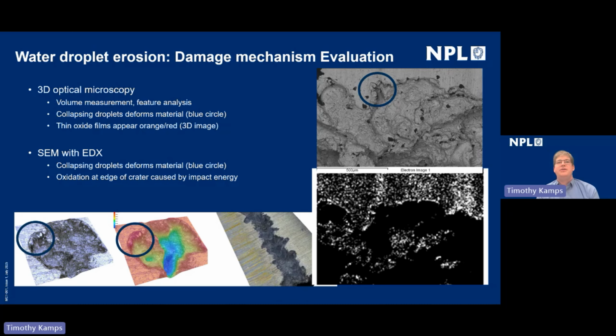And you can see the blue circle identifying a region on the 3D images at the bottom left of the slide, with the scanning electron microscopy image on the right-hand side of the slide. This scanning electron microscope also had the ability to use EDX, energy dispersive X-ray spectroscopy, to identify elements on the surface. And in this case, we were looking at oxidation that's been caused by the extremely high strain on the sample due to the lateral jetting as the water droplet collapses.